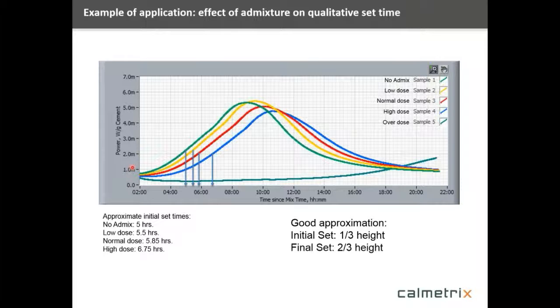actually do this particular application with the semi-adiabatic. So we're looking at power here versus time. And you can see graphically there are differences between these five samples. One thing we're going to do here is look at the initial set times on this example. A good approximation that we use is that if you look at the peak height here, about a third of the way up is considered the initial set time. And about two-thirds of the way up on the peak height is considered the final set. So illustrated in blue here, these arrows, is a qualitative assessment of the initial set for these four different samples. And so the initial set times range from about 5 hours to 6.75 hours in this example.